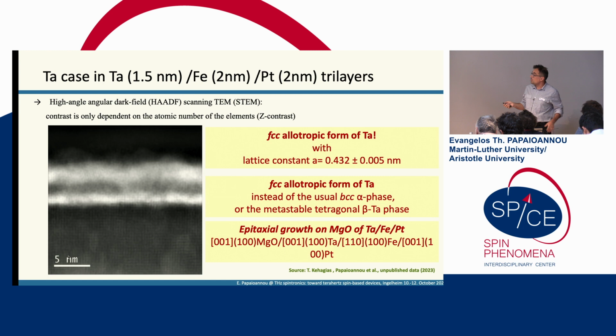However, the new thing that we discovered is that this form of tantalum does not normally exist. Everybody knows about the alpha phase of tantalum, which is the BCC phase. People in spintronics try to make the beta phase of tantalum, which is a metastable tetragonal phase. But this is an FCC phase, an allotropic phase. I think we now leave it to the theoreticians to try to calculate the spin-orbit and the spin band coupling here, in order to explain our data.